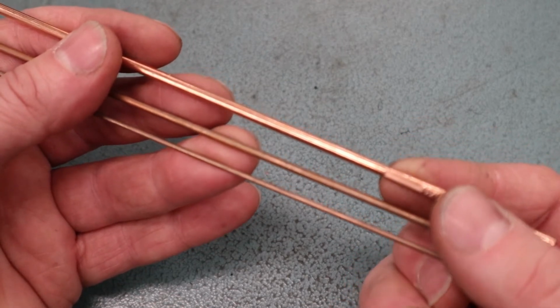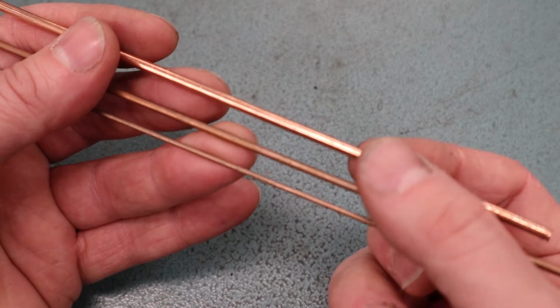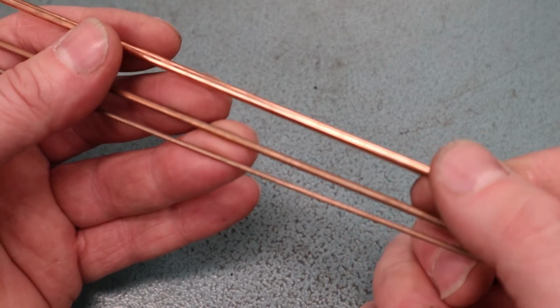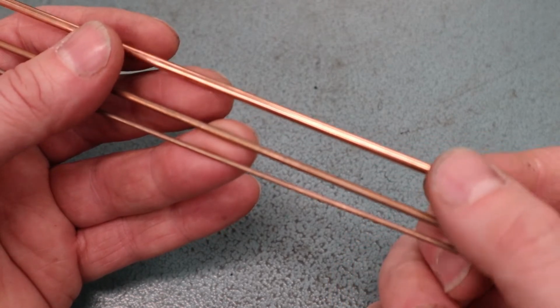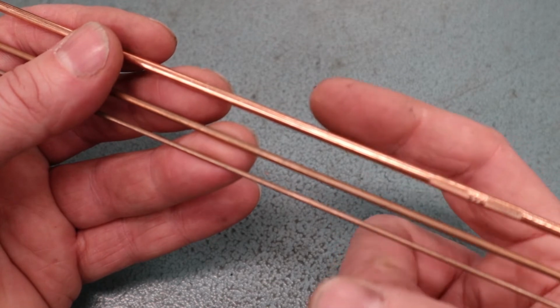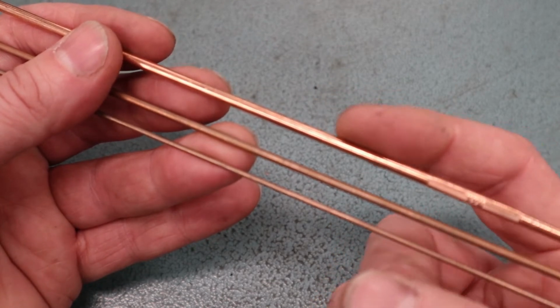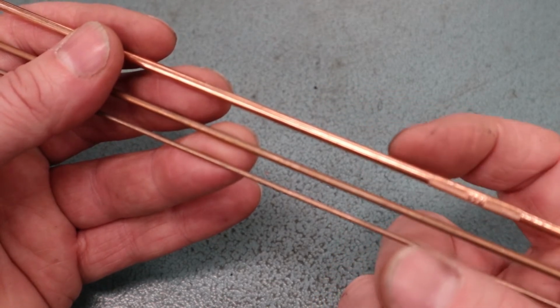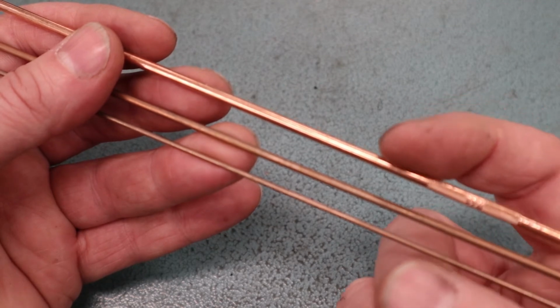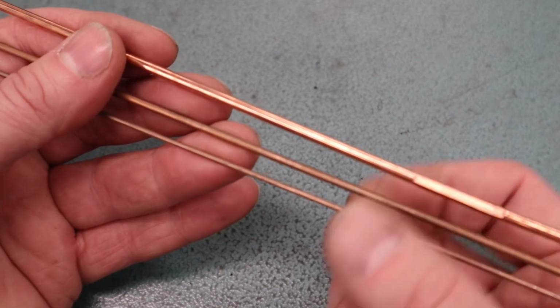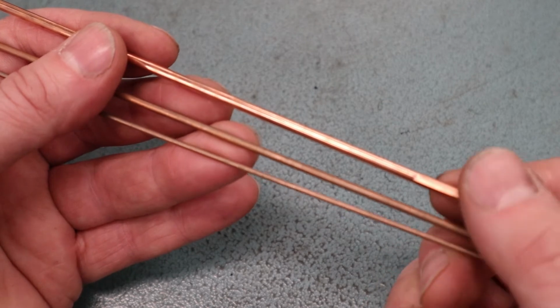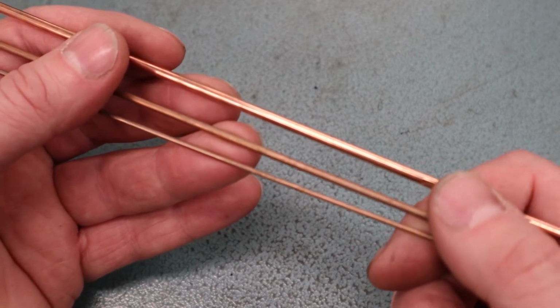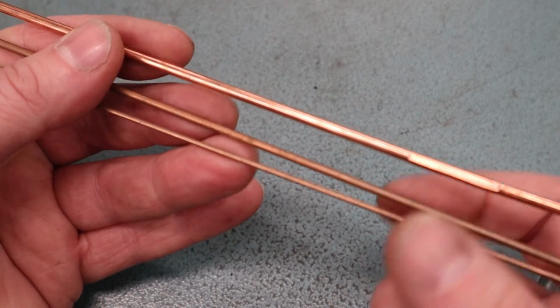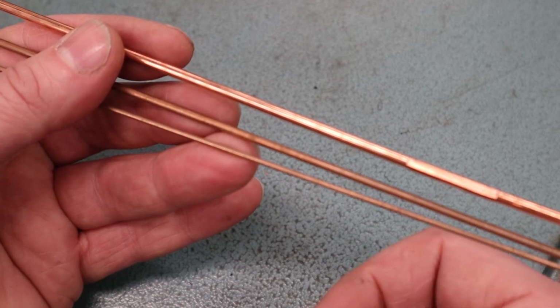So for my samples, I was using carbon steel. So these are carbon steel filler rods, except they look like they're kind of shiny and they've got copper on it. And that's because they are actually coated with a very thin coating of copper to prevent these from rusting. And then when you weld with these, that thin layer of copper just melts off and doesn't interfere with your welding. But if I was welding aluminum, I'd have some aluminum filler rods or stainless, so match with whatever you're doing for your base materials.